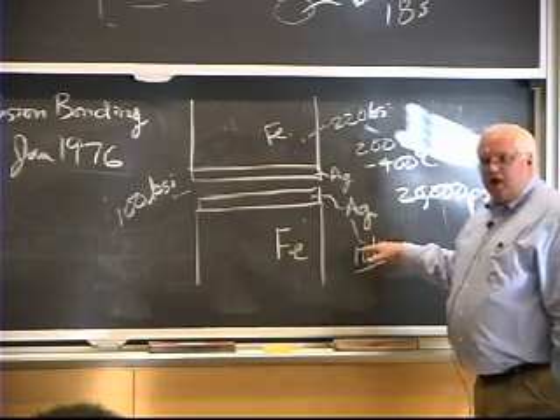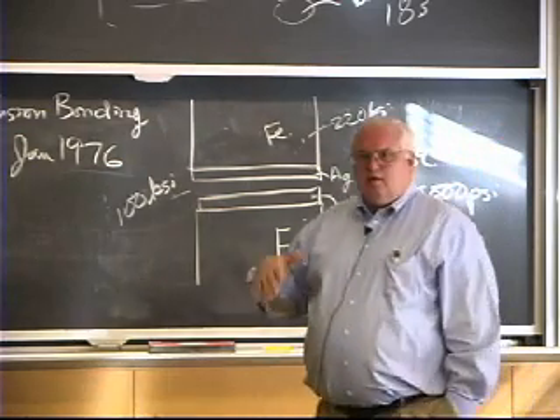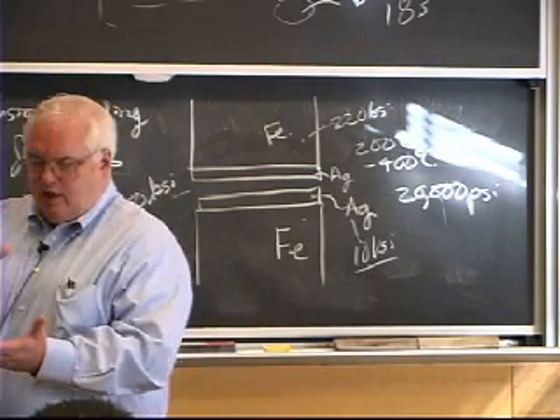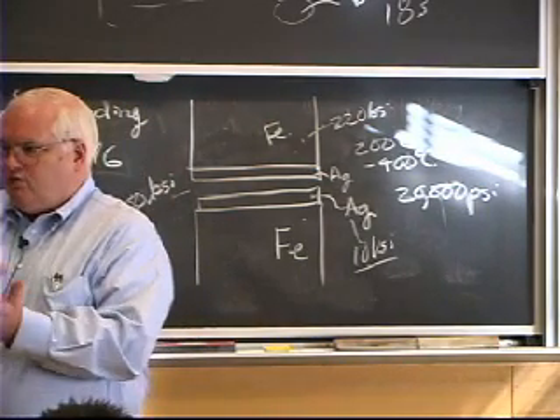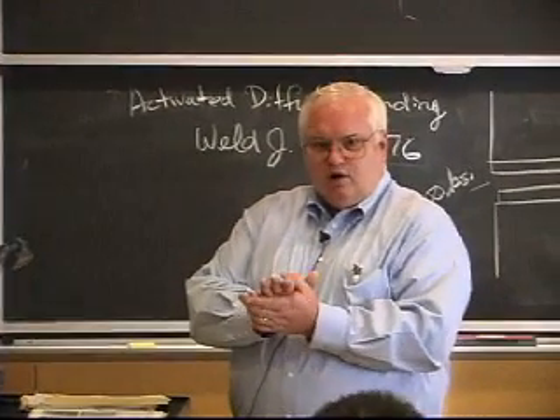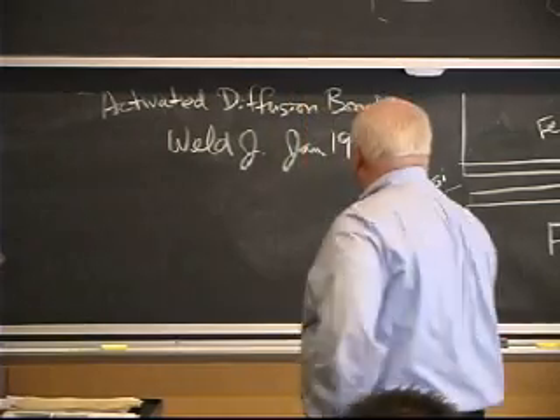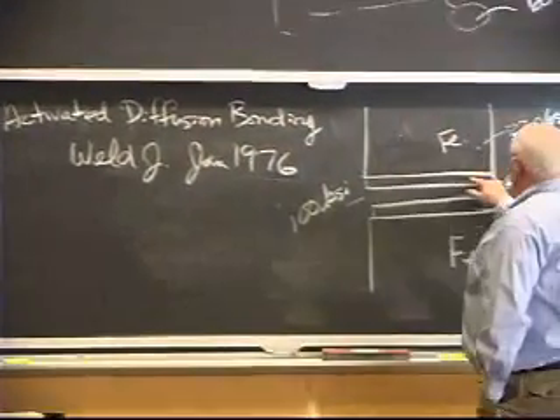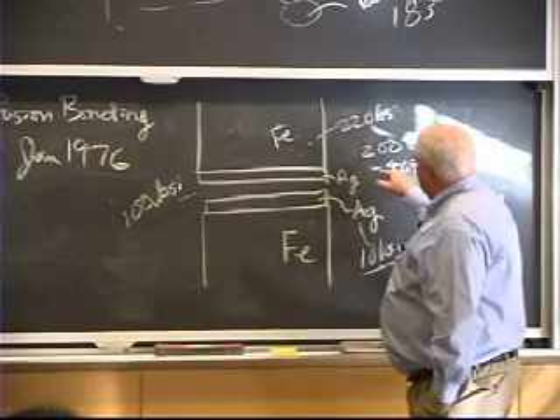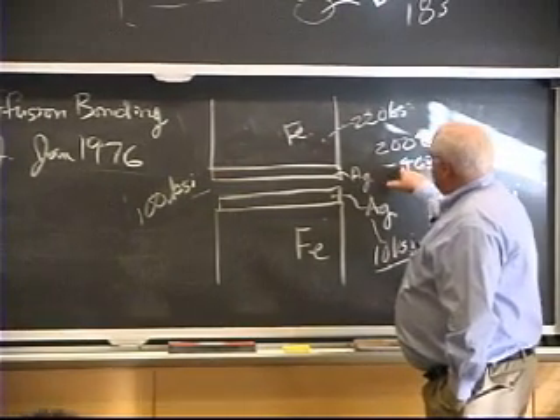So I'm pressing down with 20,000 psi on a soft material at the inner layer that only has 10,000 psi strength. And remember, the indentation pressure for a hardness test is about 3 times the compressive yield stress of the material. So they're getting up to where they're almost forcing the silver out of this joint, pressing it very hard, getting a lot of contact area, driving off the oxides with temperature, but they've changed the surface.